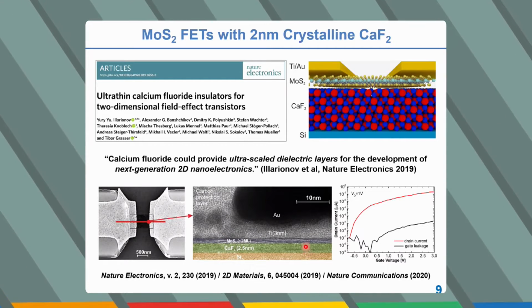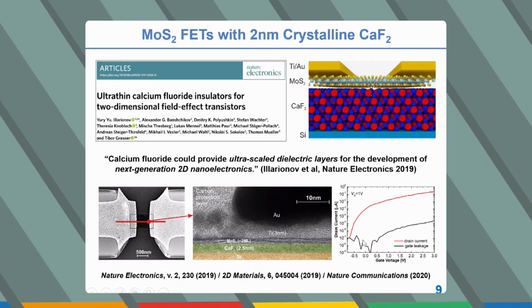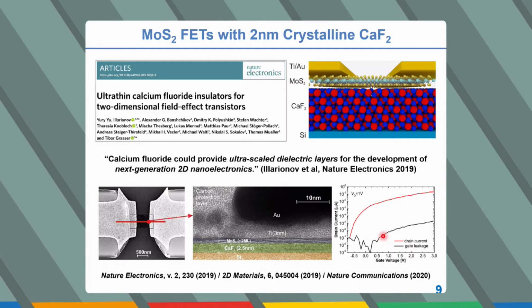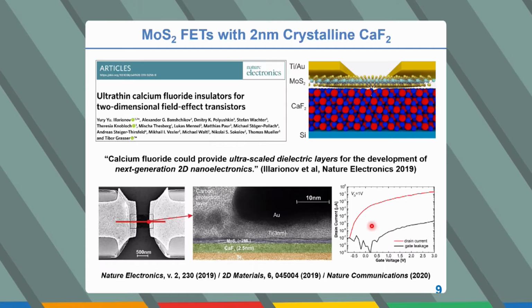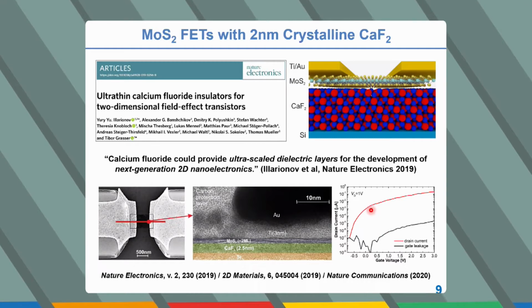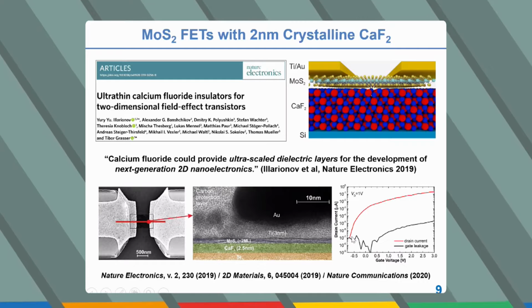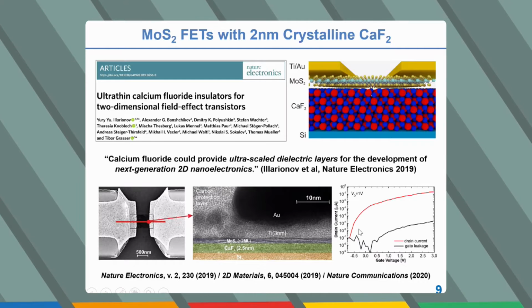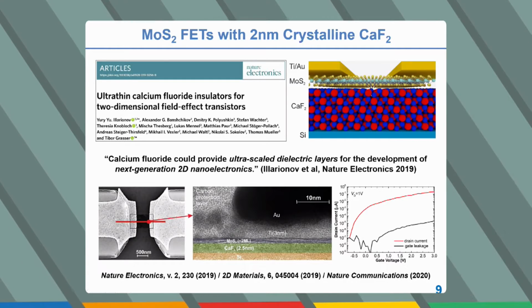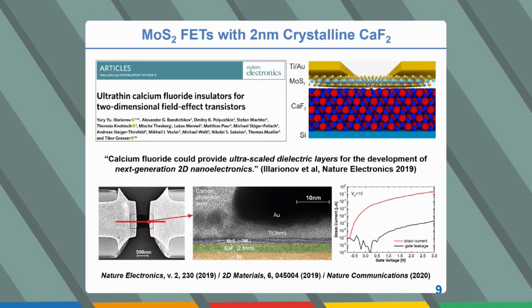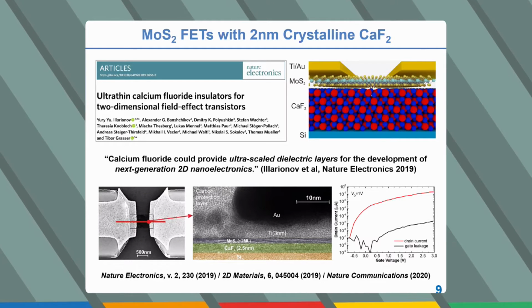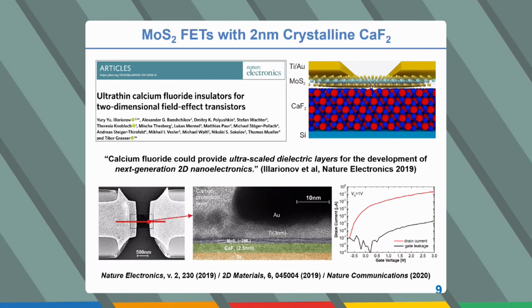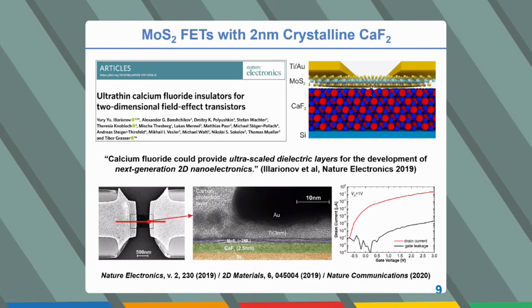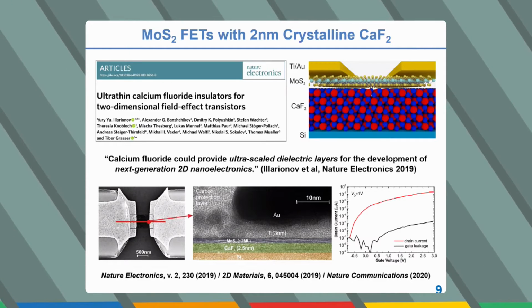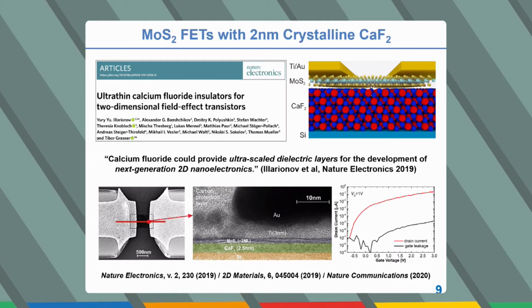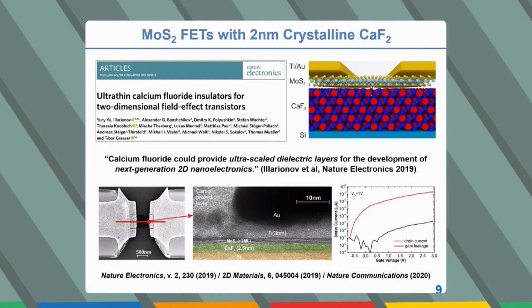And even despite the small thickness of calcium fluoride, in this graph you see that the gate leakage current is very small. It's orders of magnitude smaller than the drain current, while the on-off current ratio is as high as 10^7. So these first prototypes of devices with calcium fluoride appeared better than all previous devices with high-k oxides, which do not exhibit any scaling potential, and already have scaling potential and very good device performance.